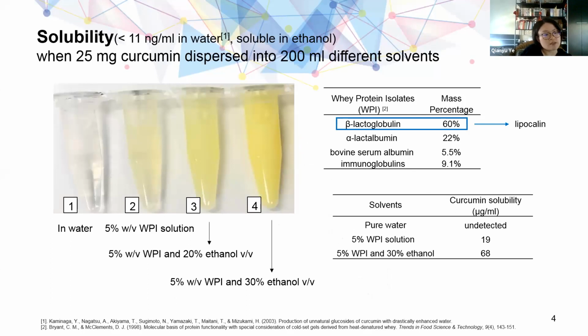The image shows the solution appearance when 25 milligrams of curcumin was dispersed into 200 milliliters of different solvents. Curcumin is nearly water insoluble. With the addition of WPI, the solubility of curcumin increased to 19 micrograms per milliliter. This is because the main component of WPI is beta-lactoglobulin, a type of lipocalin, which is able to bind and transport hydrophobic small molecules like curcumin. On the other hand, curcumin is soluble in organic solvents like ethanol. Therefore, the more ethanol introduced, the higher solubility of curcumin measured.